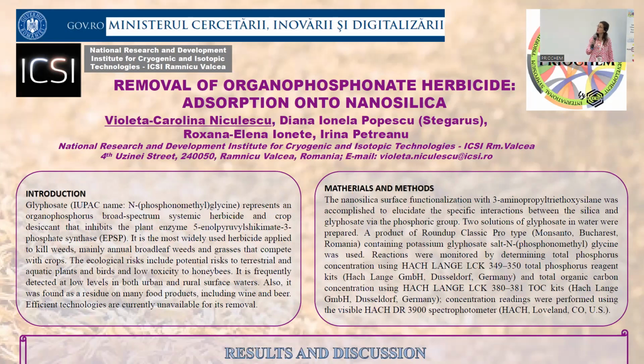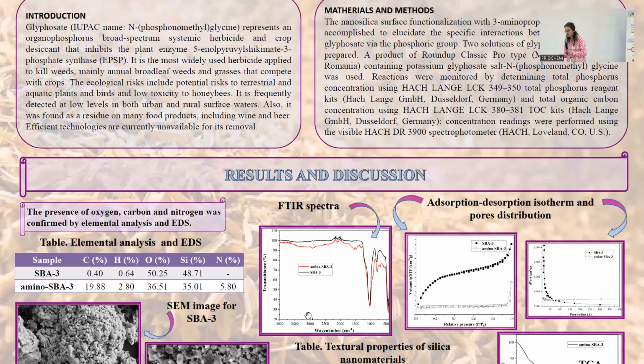And for this, we use nanosilica that we prepared, but to obtain better results, we functionalized the material with aminopropyl groups. In order to see the quality of our materials, we performed several structural and morphological analyses, and the presence of carbon, oxygen, and nitrogen in our materials was confirmed by elemental analysis and EDS.